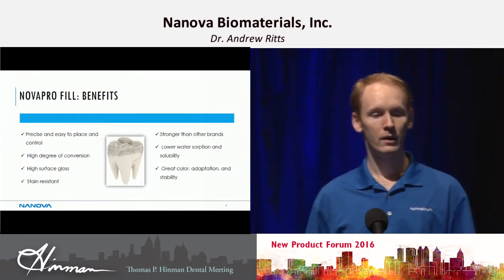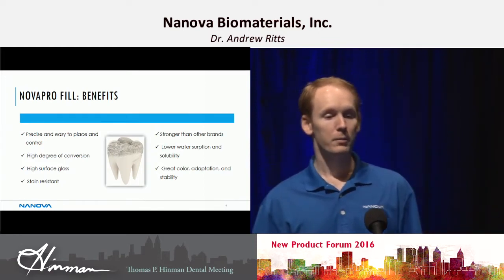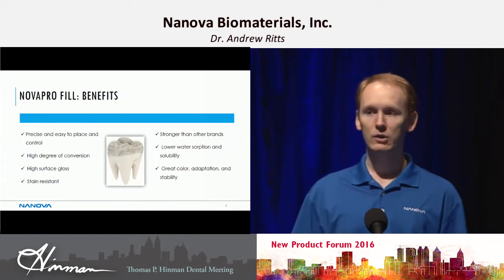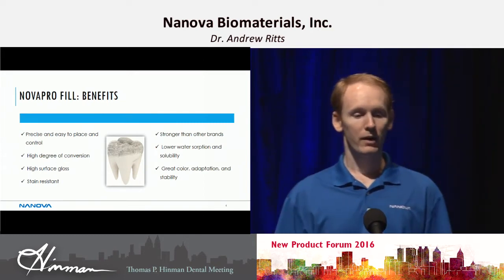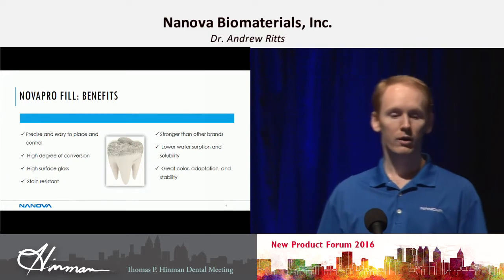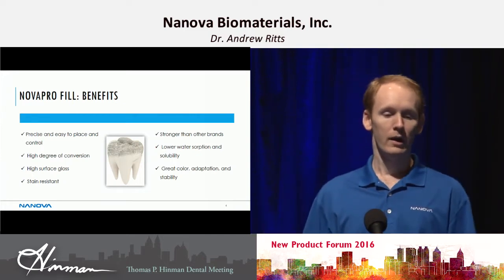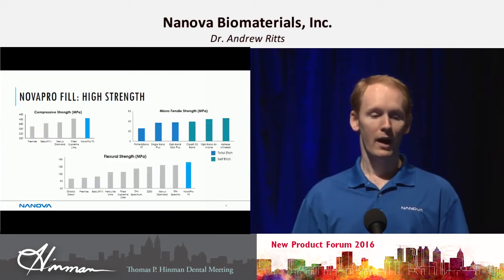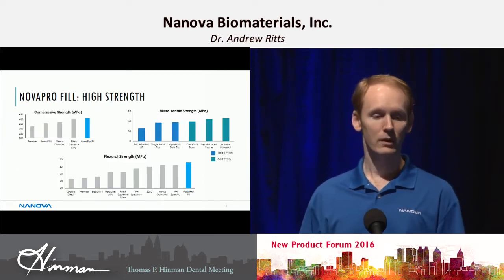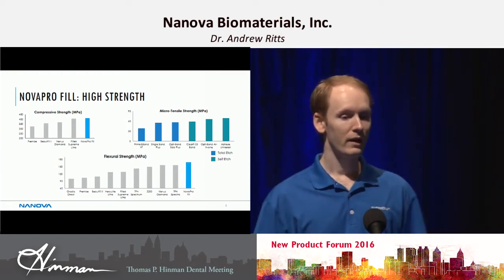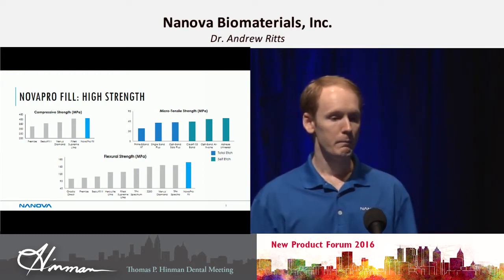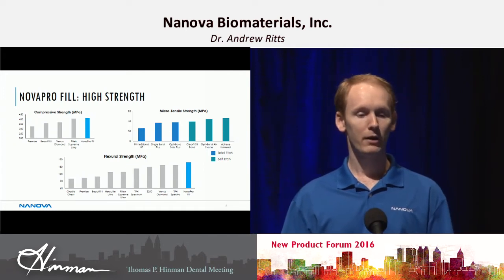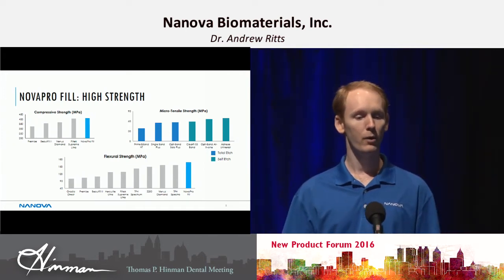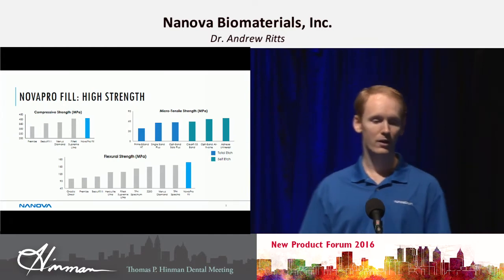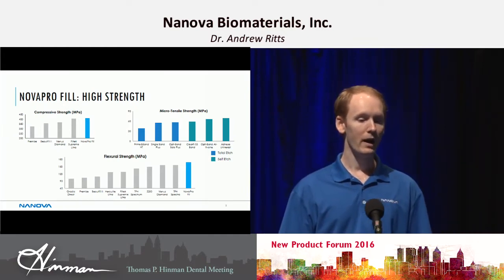So for our NovaPro Fill benefits, it's very easy to use, handle, and place. We have great color adaptation. It's stronger than many of the other brands on the market. It has very low water absorption and solubility, high surface gloss, high degree of conversion, and is stain resistant. If you look at our high strength, we have very high compressive strength, microtensile strength to many different adhesives, both total etch and self-etch adhesives on the market. And we also have a very high flexural strength.